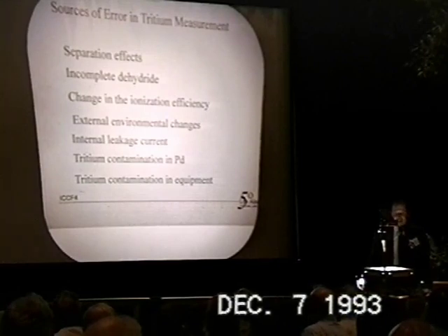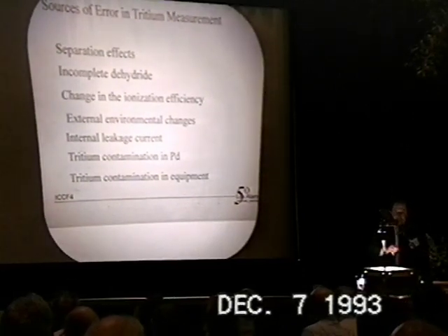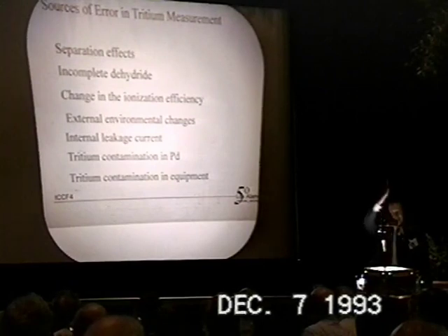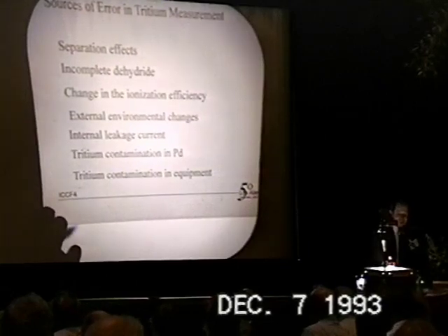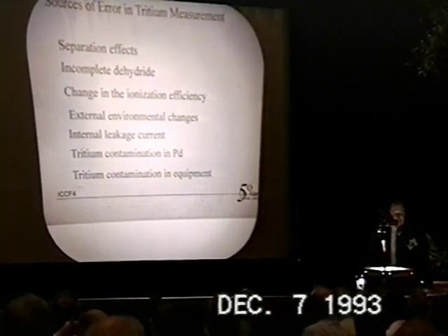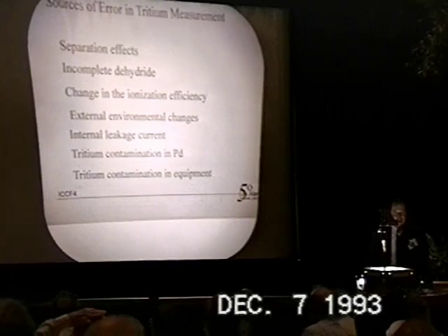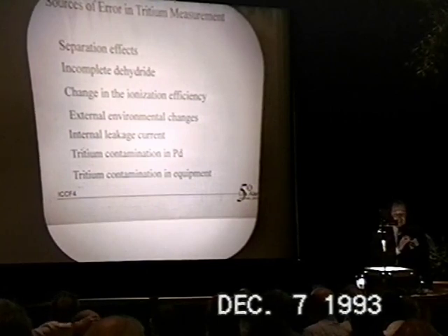Short-term changes, such as mote particles or large ions coming in, are taken care of by time. You can see these fluctuations, you see a large increase, and then the signal will settle back down to the original value. One of the largest things we've seen is water vapor off the samples. There's metal oxide on, particularly, the first cells we run, when the hydride produces water vapor, and that is in the chamber. It definitely has an effect. And we'll see some of that later.